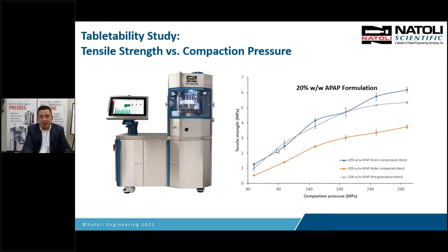Same thing with roller compaction. You'll increase the flow and bulk density. You'll achieve your flowability and your output. And you can achieve your strength at a relatively medium kind of pressure, 130 megapascals. That's kind of low, actually.